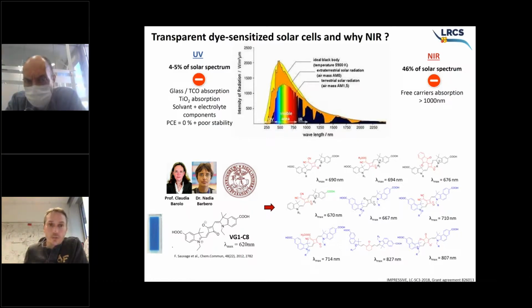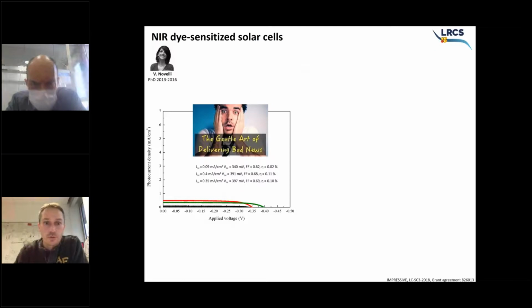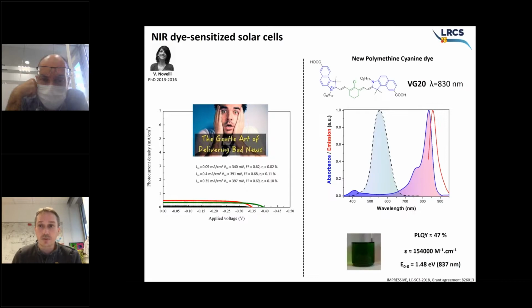This has been a very long road, going back and forth between our two groups, and this was the work of Vittoria Novelli in my group. So we were synthesizing in collaboration with Torino new dyes, and going back and forth between syntheses and devices was for a couple of years delivering always bad news. We spent time in syntheses, but efficiency-wise it was always in the range of 0.1, 0.2, 0.3%. And then came this very interesting dye.